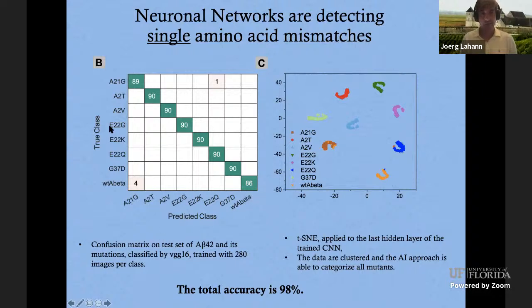And then when we run the different test images, so these are images that the network never saw, against training images, we get to predict the composition of the peptide with 98% accuracy. So we can, with 98% accuracy, predict which mutation happened in this particular protein. And the ones where the network misses it, we always give the fault to the network. In those cases, we can go back and then understand why it missed it.